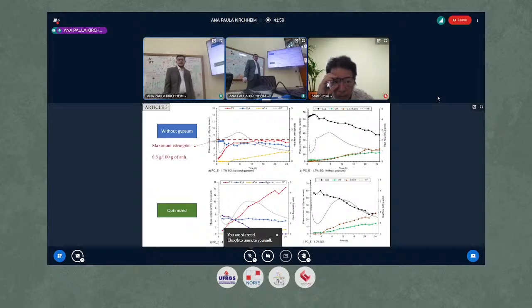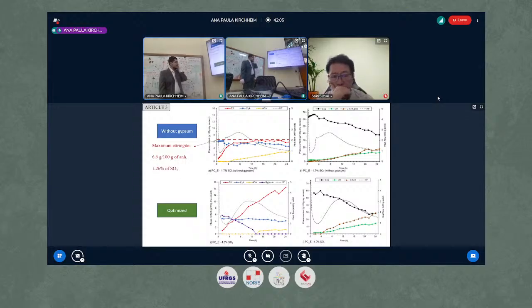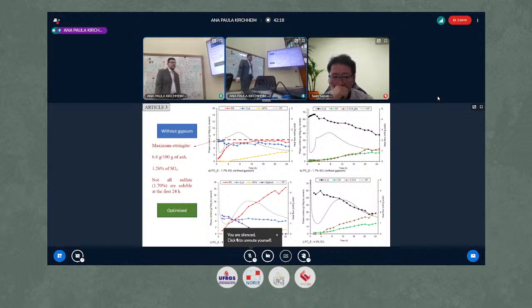we can calculate how much sulfate would be expected. 1.26% of sulfate. So not all of the sulfate is going to ettringite. So perhaps not all of the sulfate is soluble, because we have sulfate in belite and in alite, as shown in the previous study.